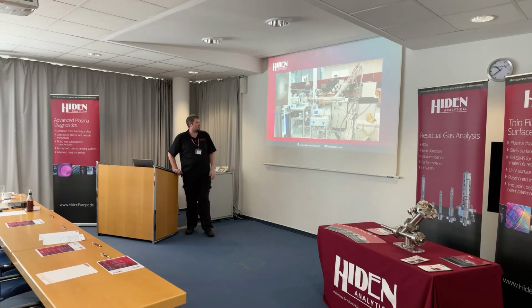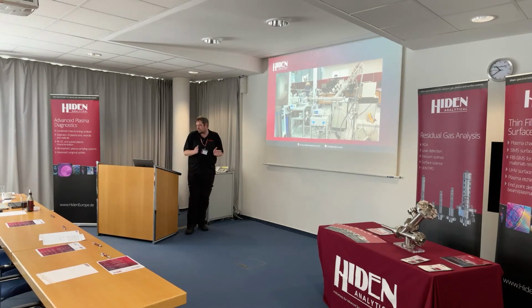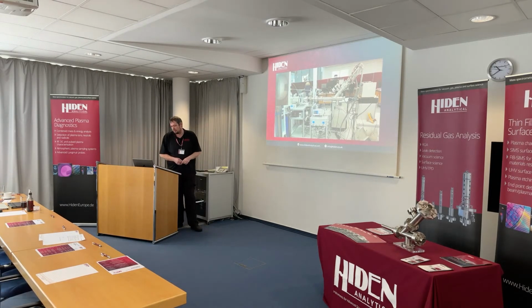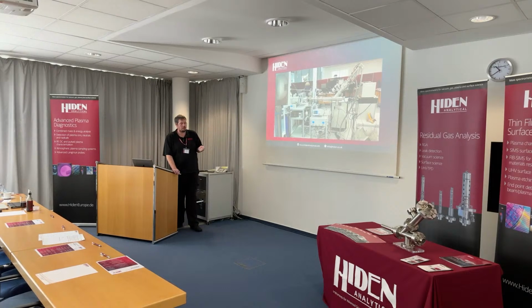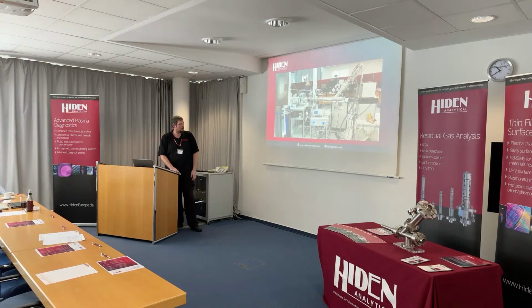It's a capacitively coupled plasma. You can see the view through the window in the top corner. The electrodes are on the left, the EQP is on the right, typically kept about 5 to 10 centimeters away. It's a 13.56 megahertz plasma, so we have the matching network, and we can also pulse the plasma using the function generator, so we can do time resolved studies as well.